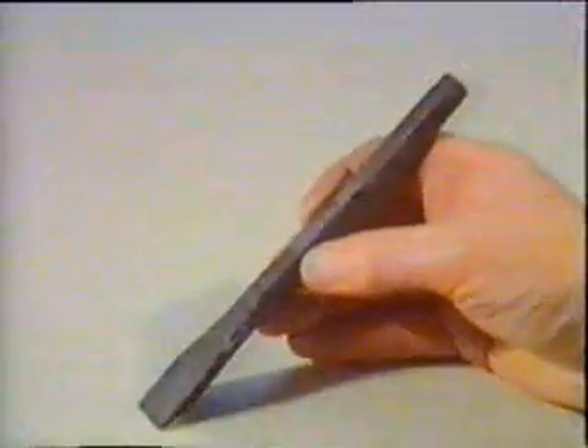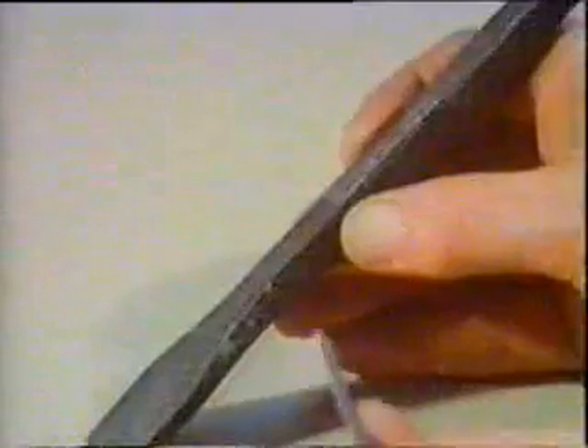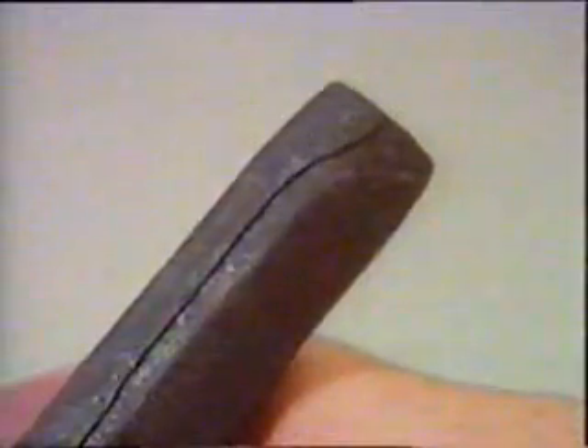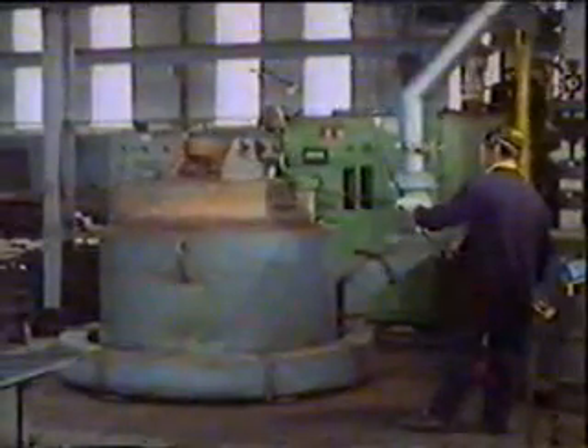Now, cooling steel rapidly in cold water from a very high temperature may do more than just harden the material. If you look closely at this cold chisel, you'll find it's cracked. It may be hard, but it's no more use as a chisel. We can reduce the risk of cracking by cooling at a slightly slower rate.